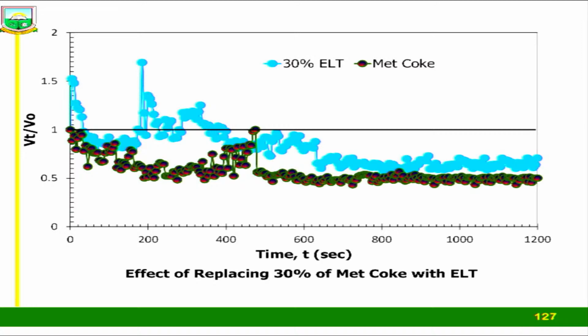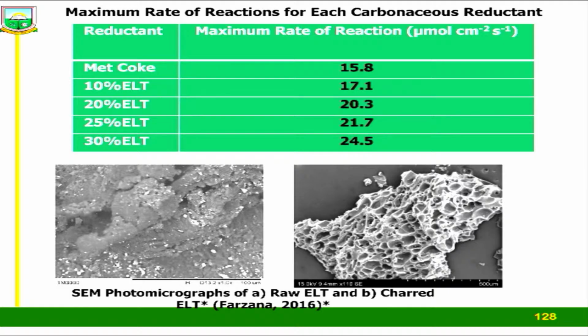And we measured the rate of the reaction. If you take a look at the slide, you notice that when we use metallurgical coke, the rate of reaction was only 15.8. And it increases progressively to 30% ELT when the rate was about 24.5 micromole per centimeter square per second. So once again, waste polymers, whether it's a thermoset, a thermoplastic, or an elastomer, are very useful materials for iron and steel making technologies, as well as the slag foaming step of the electric arc furnace steel making process.